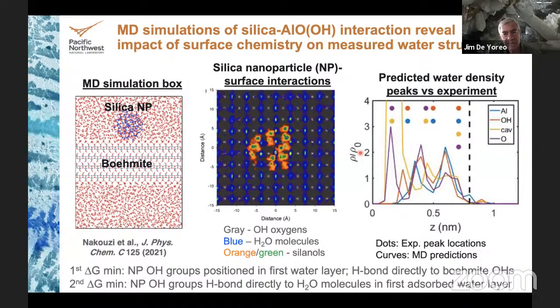So if you look at the predicted density of water relative to bulk versus height, now the peaks in water density ought to be where the minima in force gradients are. And indeed, the dots are where our minima are. And you see we have an agreement in the first water layer. And out in the fourth water layer, you can see, yes, we predict a high density over all sites. In between, it's kind of a mixed bag. We get some agreement and some disagreement. All right, so surface chemistry matters.